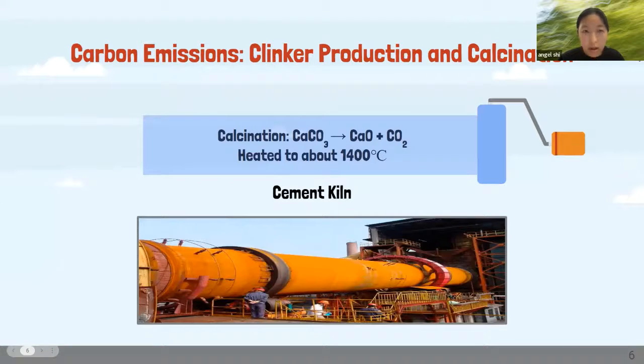So the main contributing factor of carbon emissions from the cement industry is this clinker production and calcination process. It contributes in two ways. First, the kilns need to be heated up to 1,400 degrees Celsius, and that uses a lot of fossil fuels, which releases carbon dioxide. And second, the calcination reaction to create clinkers, which is the intermediary product to produce cement, also creates a lot